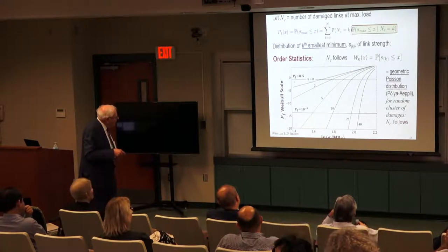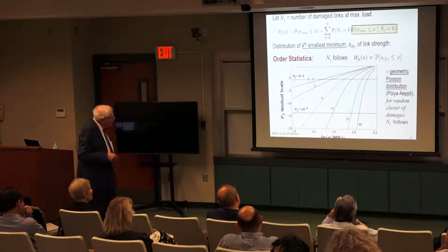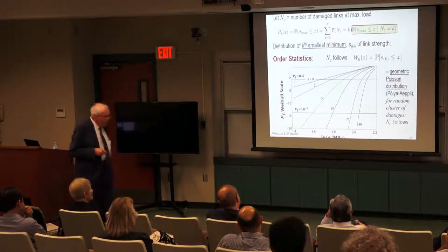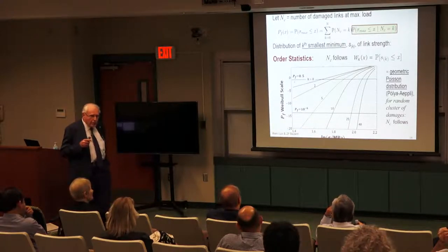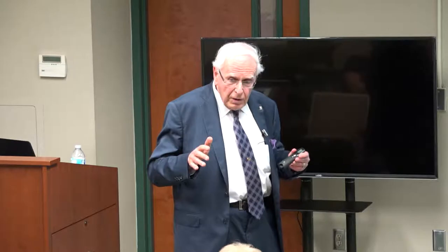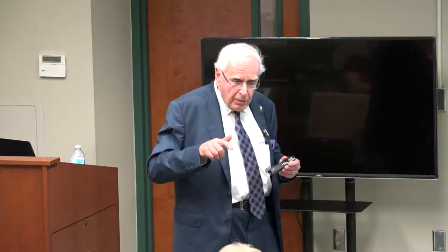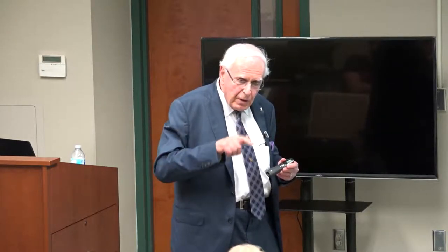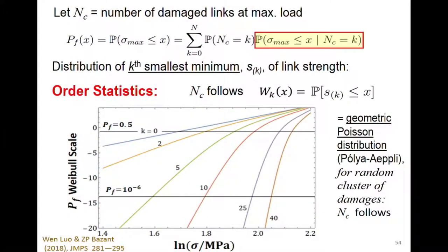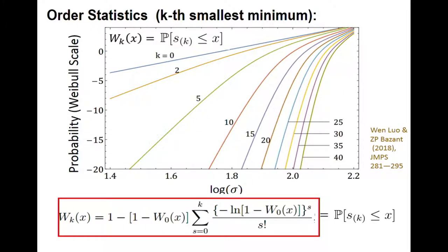And the point now is which of these distributions take. And there is a simplification also. If there is one big jump down, there is a bigger distribution of stress. If there are 20, it's very small. And after the next jump, it actually takes into account the previous jump. So you can forget about a distribution with order statistics. There's a great simplification analysis. And with this, we can calculate what happens.